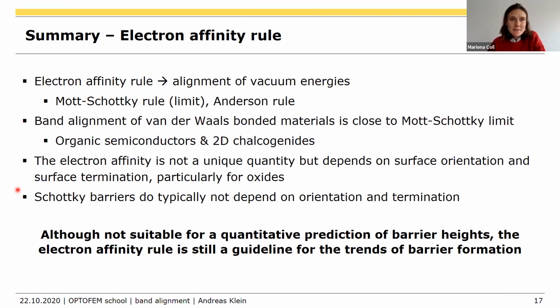So let's continue. There was one more question. Maybe I can get this also from Mathieu. Is it possible to get different offsets depending on the core level you choose as a reference? If you get that, something is wrong. If we have the possibility to measure different core levels, we do this. I will also later show some example for Schottky barriers. If the core levels are not shifting in parallel, that's usually an indication of an interface reaction, or some extremely narrow space charge regions; different effects may occur. Usually they should give the same alignment. They should not be different. Okay.